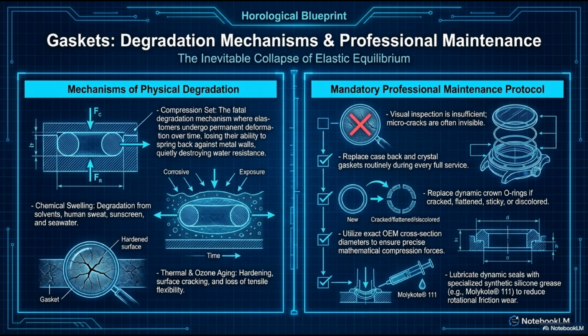The rubber absorbs microscopic amounts of cleaning solvents, human sweat, aggressive sunscreen, and seawater, causing the polymer chains to bloat and break down. The third is thermal and ozone aging. Constant exposure to UV light and temperature swings causes the surface of the gasket to harden, crack, and lose all tensile flexibility. Because of this, look at the mandatory professional maintenance protocol on the right.